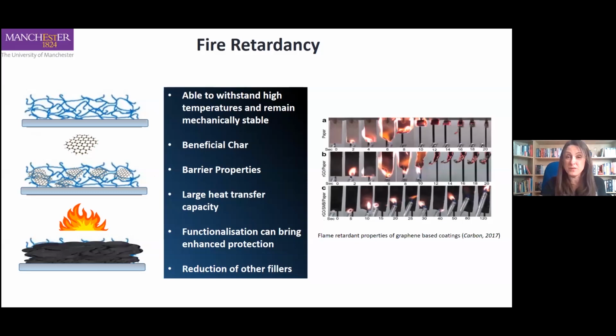Graphene can also improve the thermal stability of polymers by forming networks. It can affect Tg, melt viscosity, prevent dripping, delay ignition temperatures. There's a huge amount of work in that area as well, and especially if you're looking at graphene and graphene oxide based flame retardant materials.